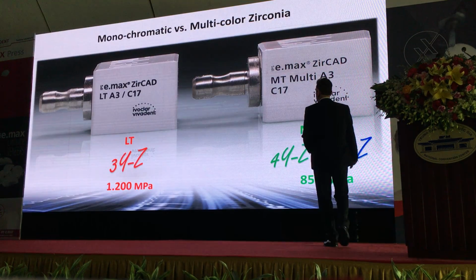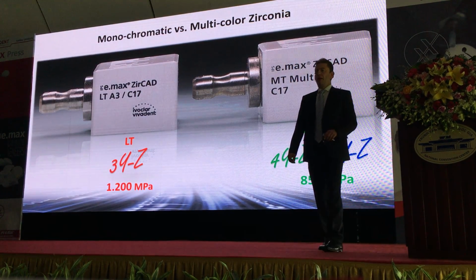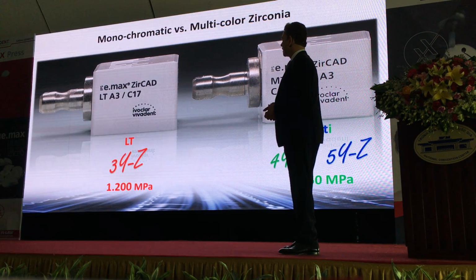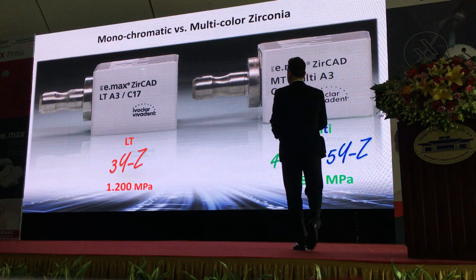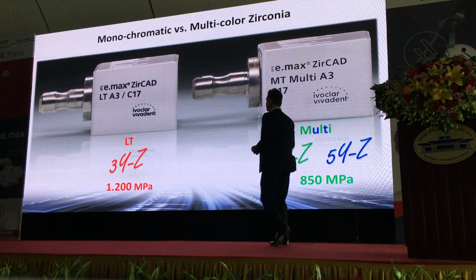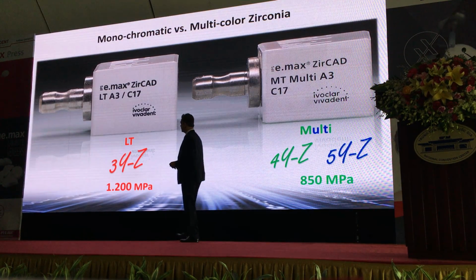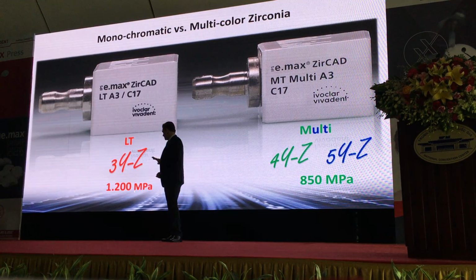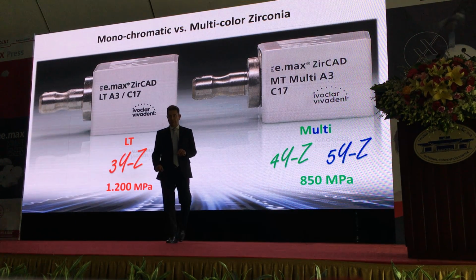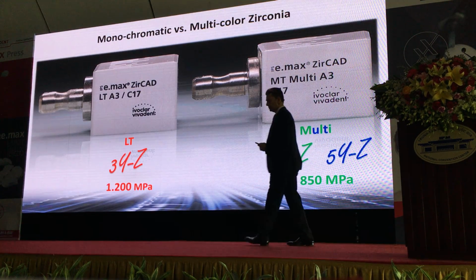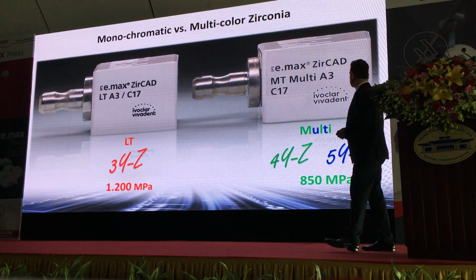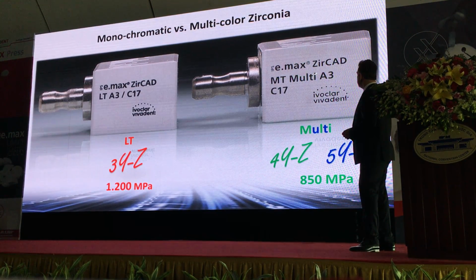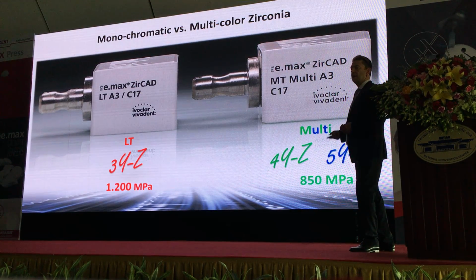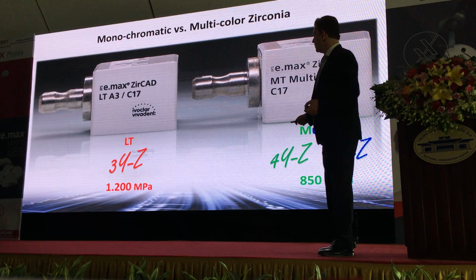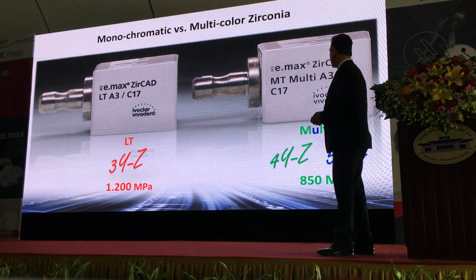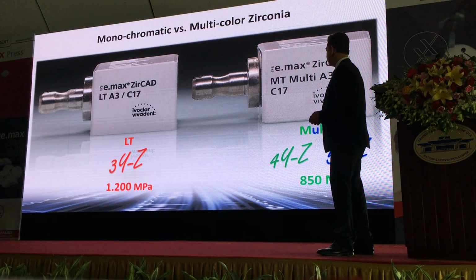Okay. Good. So I would like to introduce to you two materials of Ivoclar, which I have experience with. It's called Emax ZirCAD. This one is LT. So LT means that this is a 3YZ zirconia, not so translucent, but it has the full strength of 1,200 megapascals. And there's a new material called IPS Emax ZirCAD Multi, MT Multi. So this one is multicolor and multi-translucency also, because it consists of two raw powders, 4YZ and 5YZ.